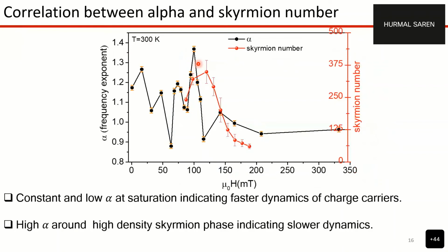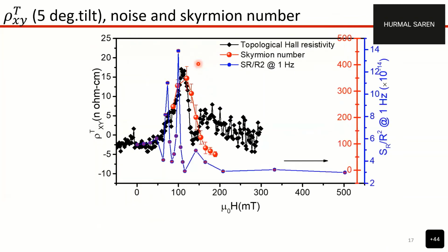Charge carriers. In this analysis, we have taken data from different instruments like SQUID, MFM, and for the transport measurement. So we are expecting that there might be some field mismatch. To investigate that, we have tilted the sample with respect to the z-axis and done the transport measurement.